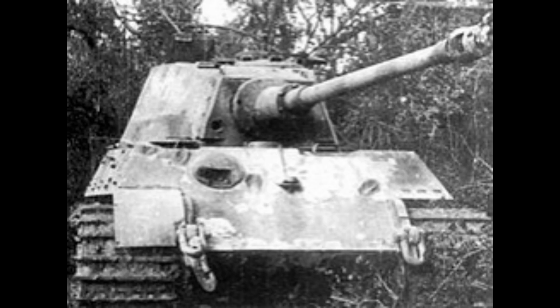Molybdenum, critical for high-temperature strength and resistance to stress fractures, was nearly absent in Tiger II plates. Samples showed less than 0.1% molybdenum compared to 0.4 to 0.6% in earlier German armor. Manganese content had increased to compensate for missing alloying elements, but manganese alone could not replicate the properties of proper armor steel. Chemical analysis revealed the extent of material degradation.